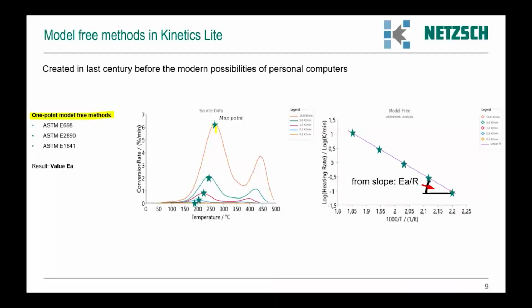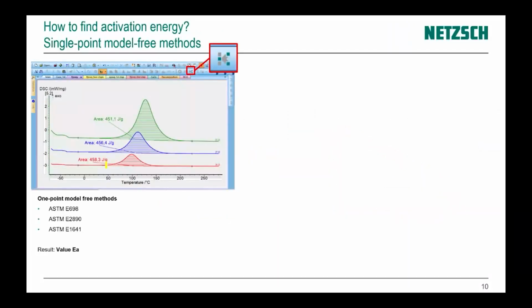One of them, for example, takes only one point for each curve. Here is the maximum point. All other information is lost. Then these maximum points are presented on the Arrhenius plot, where the horizontal axis is 1 divided by absolute temperature. Vertically here, for the Ozawa method, is the log of the heating rate. Then we have a straight line. All points are on the straight line, and the slope is proportional to activation energy. So from the slope we can find the activation energy, and it is only one value, and it is a very, very fast example. Now the question: can we find activation energy from single-point model-free methods?